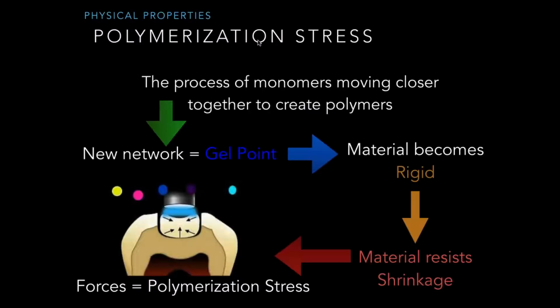This illustration gives a great visual understanding of what happens during polymerization. As a composite cures, we know that there's a volumetric shrinkage that occurs, but also a physical stress translates on or within the tooth. Essentially, stress becomes the force that the shrinking composite exerts on the surrounding tooth structure. Think for a moment if the material is insufficiently polymerized or is an inadequately cured composite material. This then becomes a significant violation of the foundational integrity that I was just talking about. Physical and chemical properties of the material you relied on are now adversely affected, allowing for a weaker restoration, weaker properties, sensitivity, and decay. And then if you also consider if the material is not properly adapted to the preparation geometry, again, you've violated some key points here. The lack of foundation integrity compounds the risk.